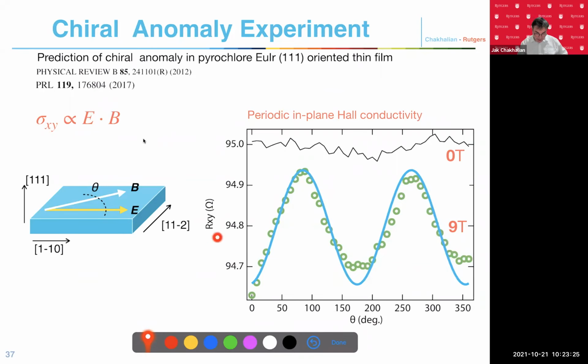And really, this is the whole effect. This is the rho XY, so this is the transverse resistivity, like in the Hall effect. And it oscillates as predicted by the chiral anomaly. This is the axial current. So it's a fully topological result. And once you turn it off, it's a control check. Of course, it disappears, right? So it's not some funny magnetism sitting inside. It's really the chiral anomaly. So to my knowledge, this is the first result which clearly shows the presence of chiral anomaly in this 111 oriented film.